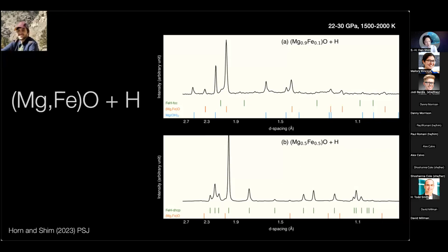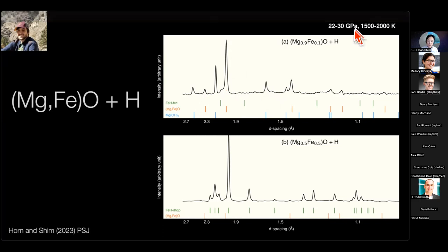With this, we recently have published a paper on our first experiment using MgFeO, iron magnesium oxide, immersed in the hydrogen and heated above the partial melting of this material. On the right-hand side of the slide, I'm showing X-ray diffraction. For those who are not familiar with this type of technique, what you see here, the peaks, are measured at a particular interatomic planar distance. So this interatomic planar distance and peak positions are characteristic of certain materials. And in fact, if we know the crystal structure of these materials, which is the case for our experiment, you can compute their expected peak locations at given pressure and temperature conditions, which you can see at the bottom of this diffraction pattern as vertical bars.